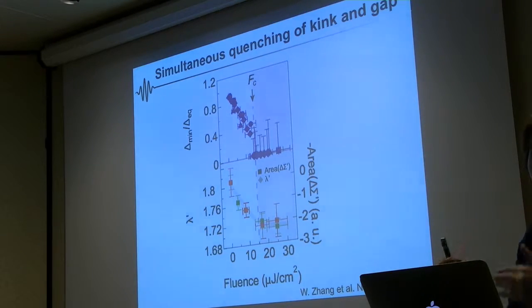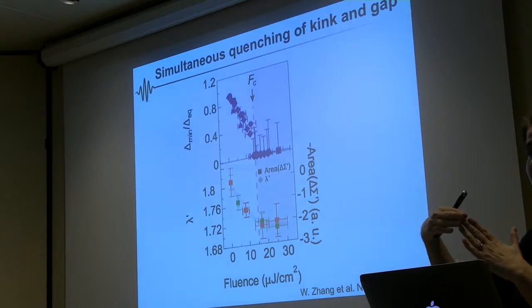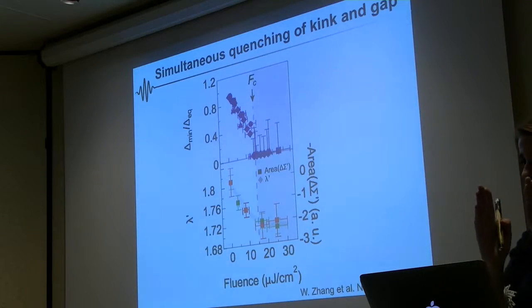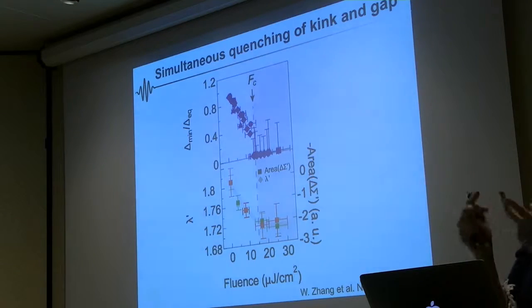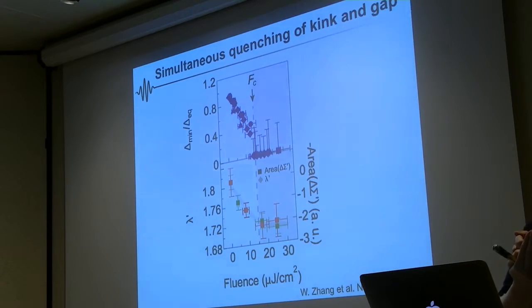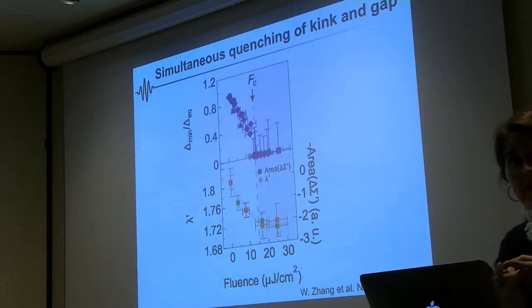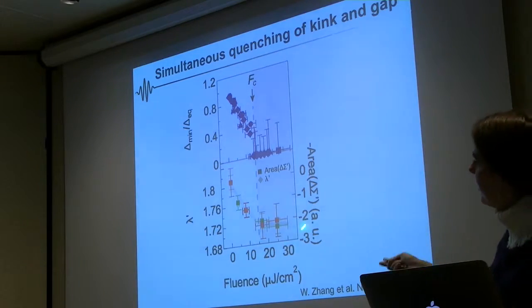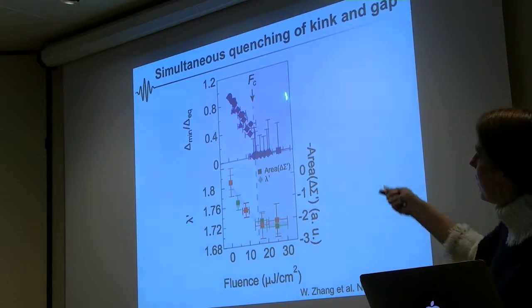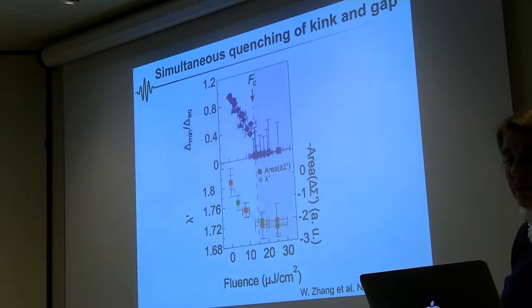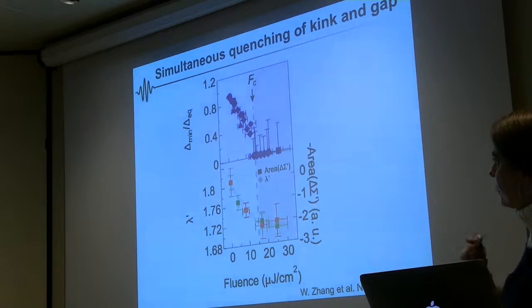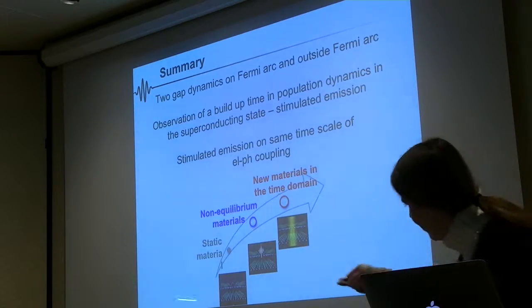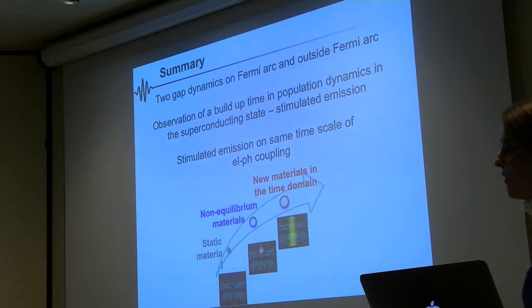see the same thing. We see that the electron-phonon coupling is a kink if we are in that energy region between 0 and 150 femtosecond, where the gap doesn't respond, and the system has this delay, then even the electron-phonon coupling doesn't respond. The moment we pass that, then the electron-phonon coupling responds very closely to the superconducting gap. And this is just a summary of the thing, and this is really where we are going in the future.